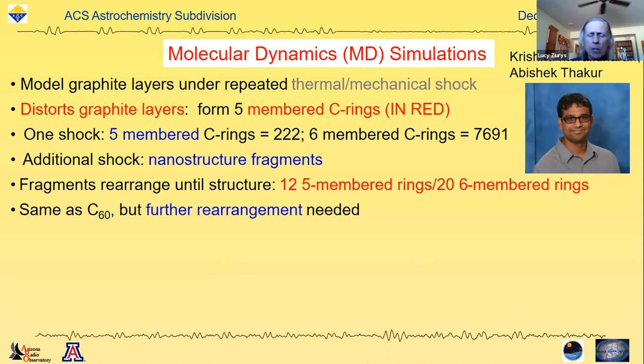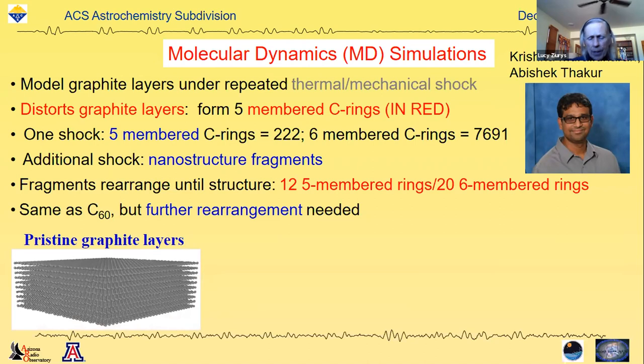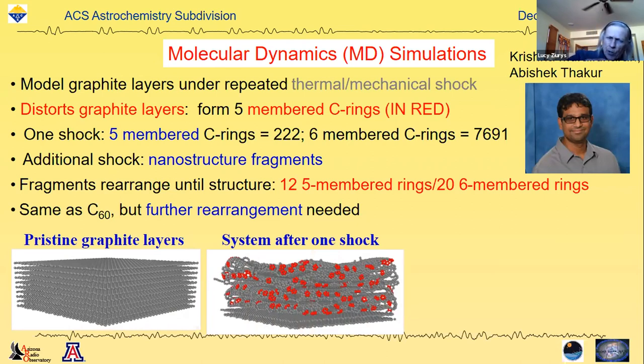They actually did some MD simulations where they took layers of graphite in a sheet, and then they subjected it to a thermal and mechanical shock, as one might find in protoplanetary nebulae. And after one shock, the outer graphite layers begin to distort. The red you see is the formation of 5-membered rings in addition to the 6-membered rings. And after one shock, we have about 222 5-membered relative to 7,691 6-membered. So there's a mixture here.